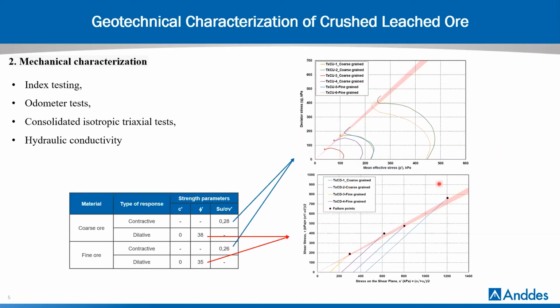In addition, CD triaxial tests were considered to evaluate the peak drained strength of the crushed ore. The drained friction angle is found to vary within 35 to 38 degrees, which is consistent with the drained friction angle of angular clean sand. The laboratory data from fine and coarse ore are processed in a similar way to obtain the table here on the left, which summarizes the parameters estimated for the crushed leached ore according to its behavior.